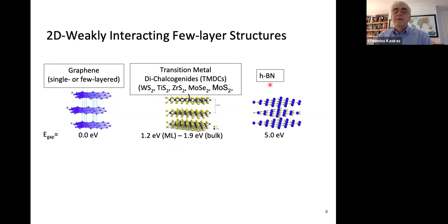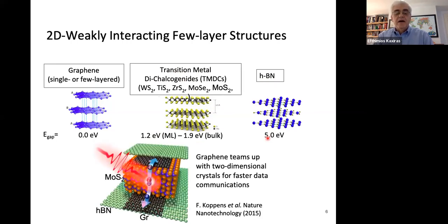And finally, the insulator, hexagonal boron nitride, which has a wide band gap and is a very nice flat material for use as an insulator. And using exactly this range of materials, people have been making devices, real devices. Here's an example with hexagonal boron nitride at the top and at the bottom, and graphene in between to conduct the electrons, and a molybdenum disulfide few layer system here where the electrons are excited, and so on. And these kinds of devices can give really quite unusual behavior, faster communication, and so on.